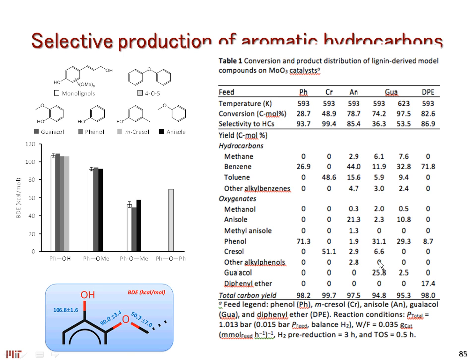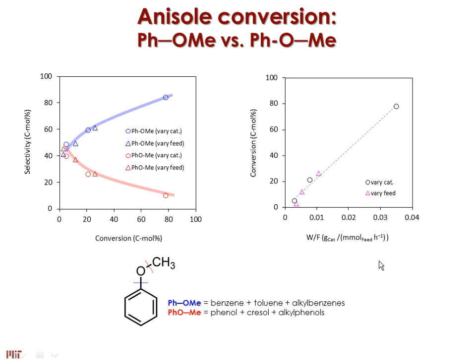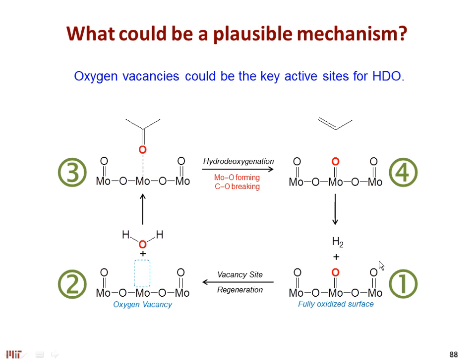So in the interest of time, I'm going to skip this, but what we find, right, is when we go to differential conditions in our reactor, we actually see a mixture of aromatics such as benzene, and then we see phenol in about a 1-to-1 proportion. So when you go to 0% conversion, this changes a little bit. But we found it very interesting that even though we should expect a lot of phenol production in the beginning, we actually saw quite a bit of benzene and toluene and xylene from alkylating these molecules as well.